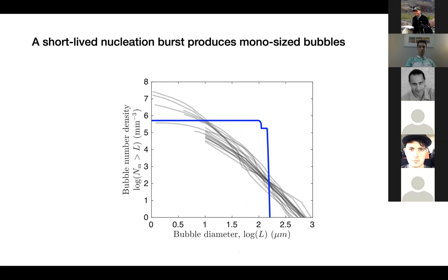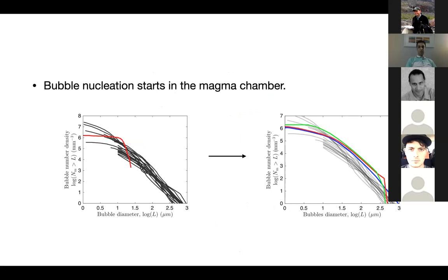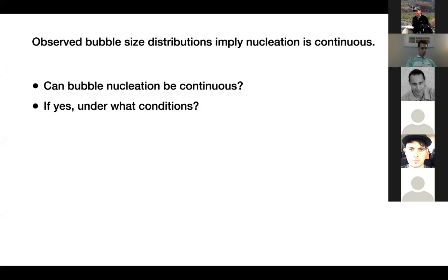That brings us to the final part of the talk, how we can reconcile bubble size distributions with eruptive conditions in these eruptions. There were several papers by Blower in the early 2000s, and also some papers before that by Mangan and Cashman, that suggested that the power law size distribution is indicative of a nucleation regime that is not nucleation bursts, but rather continuous nucleation that continues over the entire ascent of magma in the conduit.